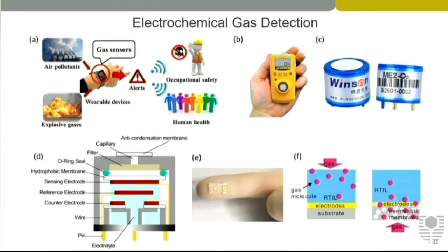The drawbacks of this design are that it's very hard to miniaturize, so you still need to use quite a lot of expensive material, usually platinum. So these electrodes are very hard to make low cost. And because of the use of a volatile electrolyte, in particular in hot and dry conditions, this can evaporate and the sensor no longer works.